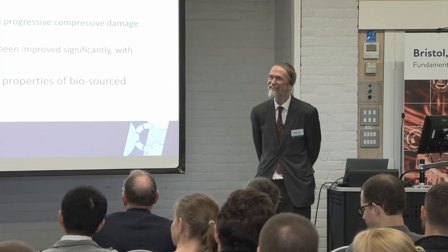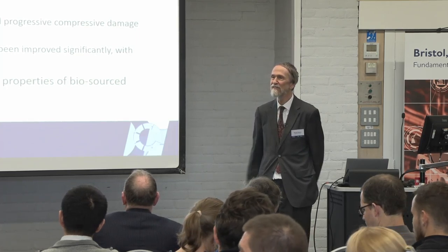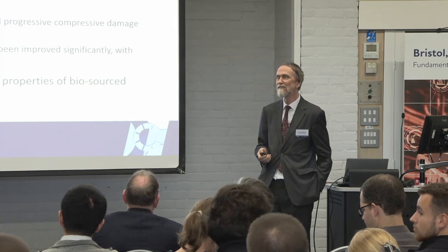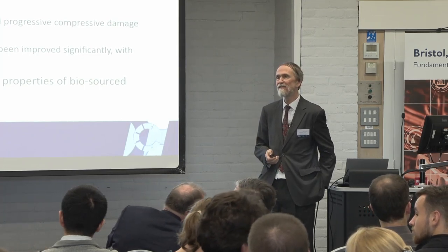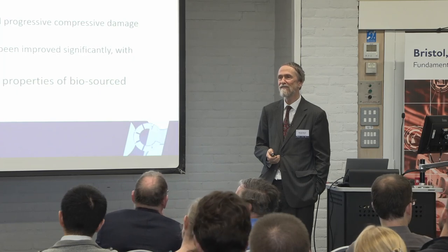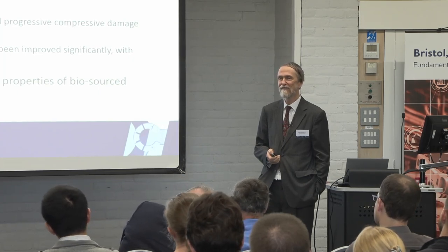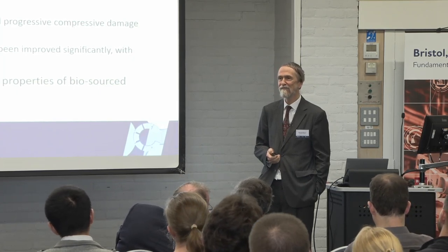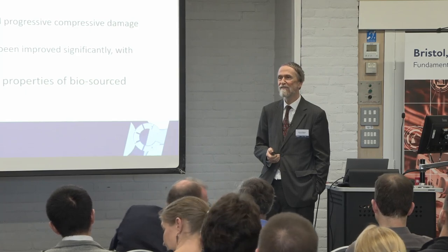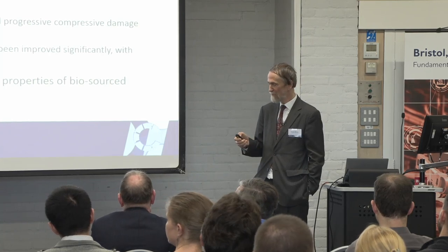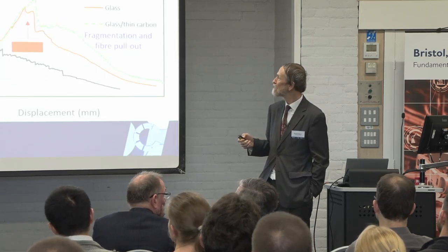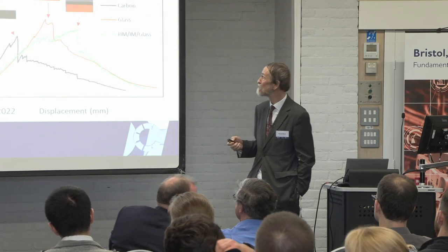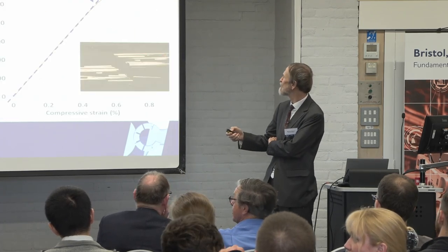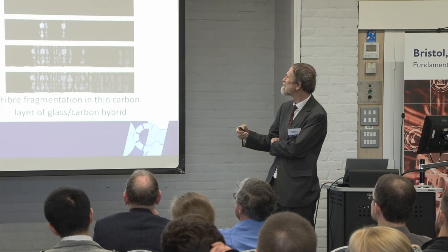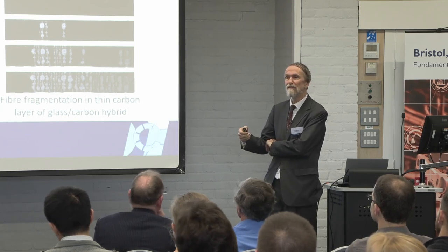Now, you mentioned the fragmentation and the increase in the energy absorption, but have you looked at the fragment lengths and the number of fragments to see what state the fragmentation is in, whether you've reached saturation or not, or whether there's some scope to go any further with fragmentation in order to achieve what you're trying to do? Because you're opening up surface area, yeah. You're converting energy to surface energy. So I just wondered whether you've actually gone as far as you could go.